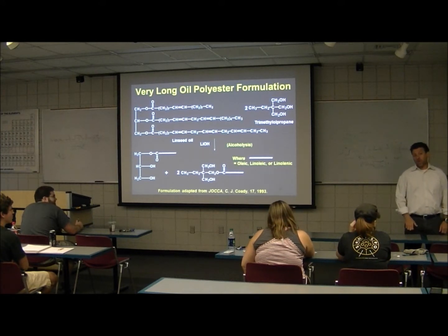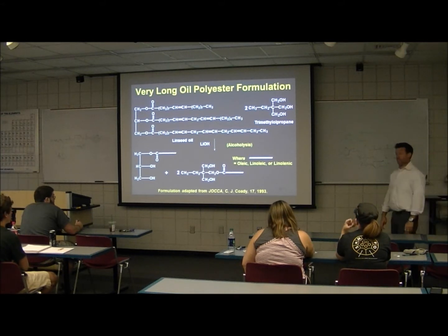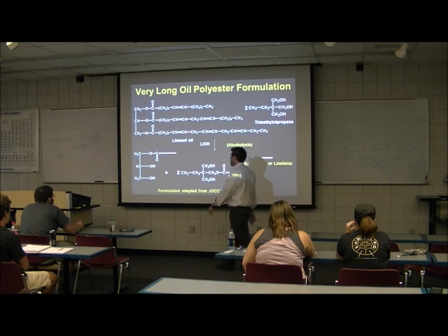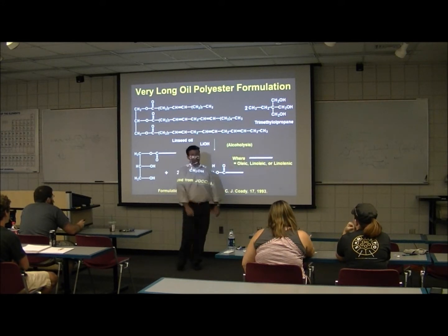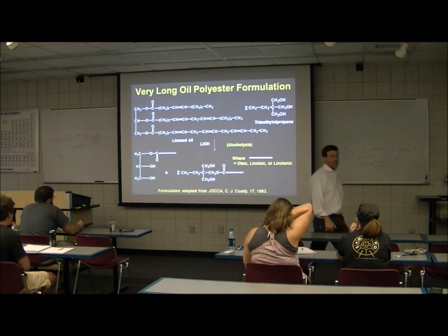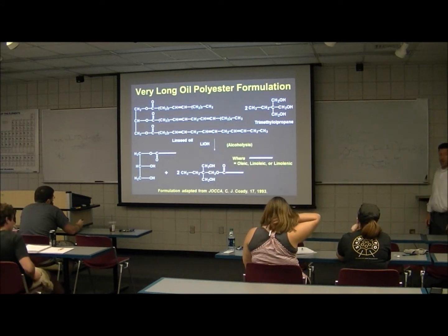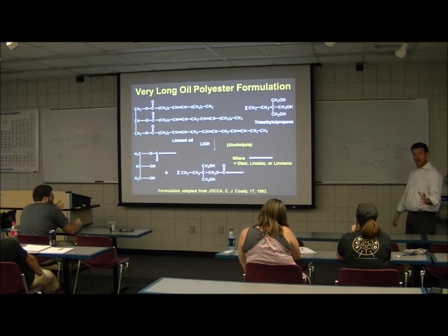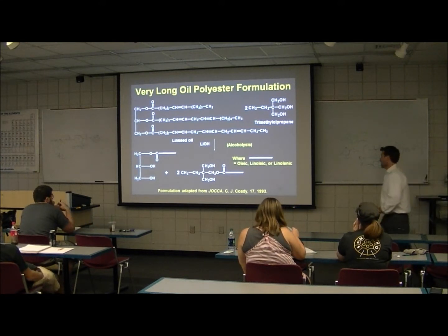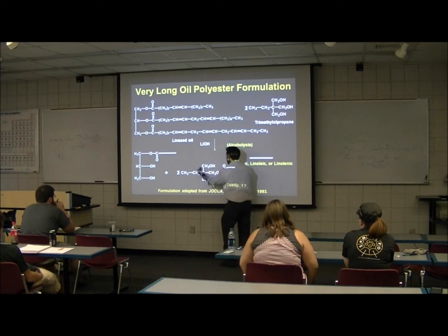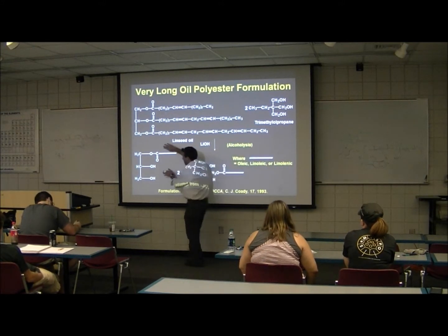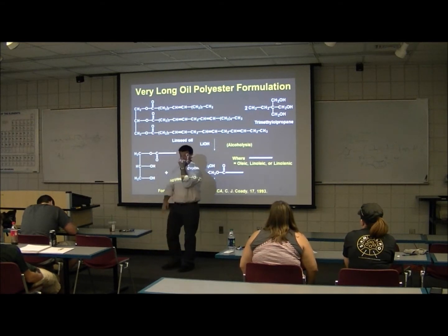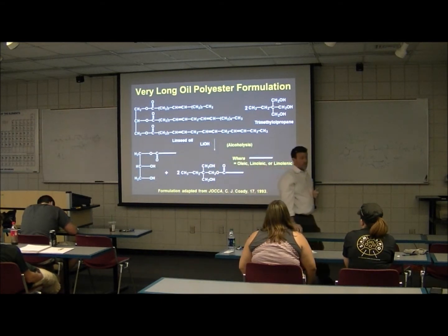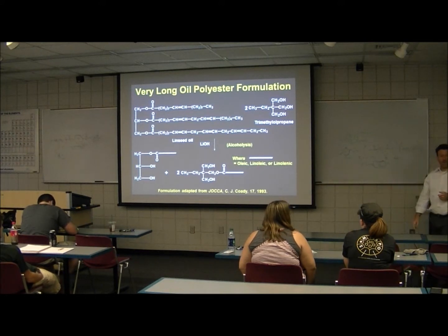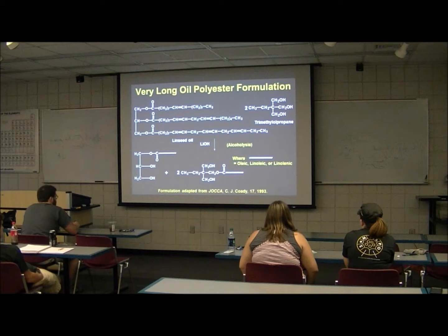And probably only carbon. So you can get lucky if the secondary is what ends up being dissociated first, and in some conditions it would be, in other conditions you'd end up with an amalgam, so it wouldn't be definitive by itself. So if we don't have an NMR, even IR turns out to be problematic, because we have the ester of CH2O, which is almost identical, right? It's almost identical in nature. This reaction is hard. It's easy to run, but it's very difficult to understand when you're finished.